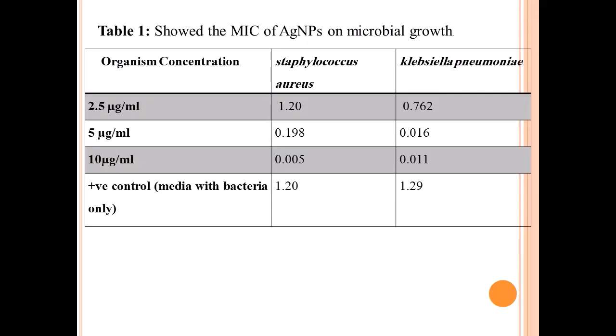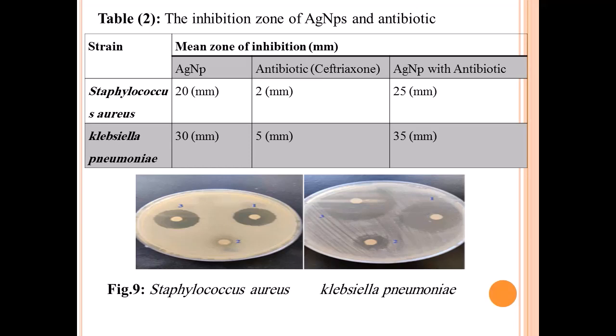Table 1 shows the MIC of silver nanoparticles on microbial growth of Staphylococcus aureus and Klebsiella pneumoniae. The concentration giving total inhibition of the bacteria is 10 microgram per ml. Table 2. The inhibition zone of silver nanoparticles and the antibiotic on Staphylococcus aureus and Klebsiella pneumoniae. The inhibition zone of silver is larger than the inhibition zone of the antibiotic, and the inhibition zone is largest when we make mixtures of silver nanoparticles with the antibiotic.